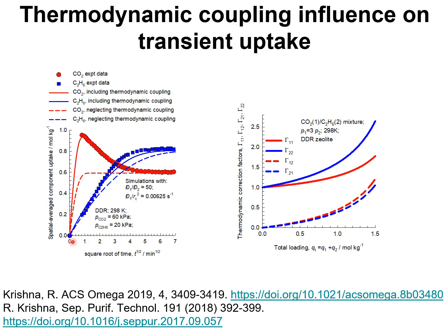The simulations, including thermodynamic coupling, correctly anticipate the transient overshoots in the component loadings of CO2 and the attainment of supra-equilibrium component loadings of CO2.